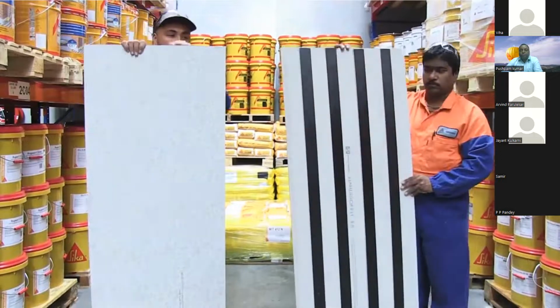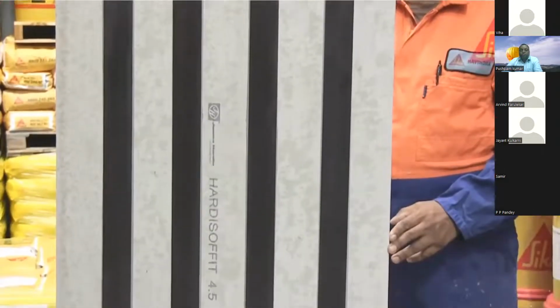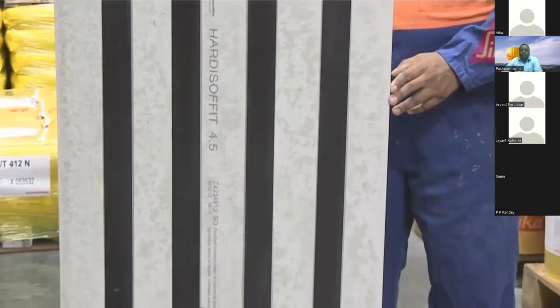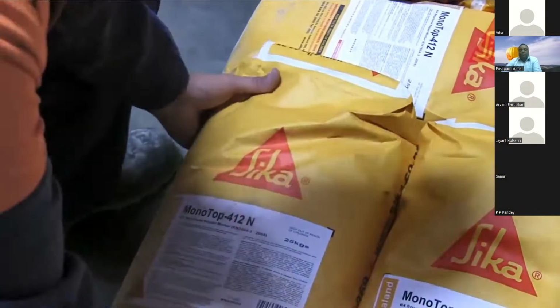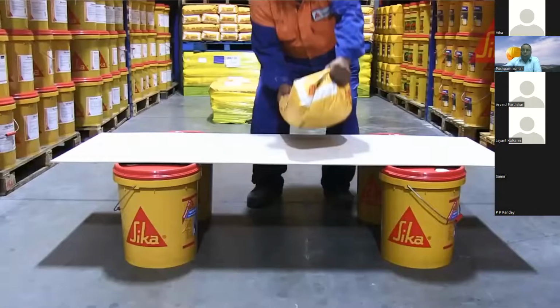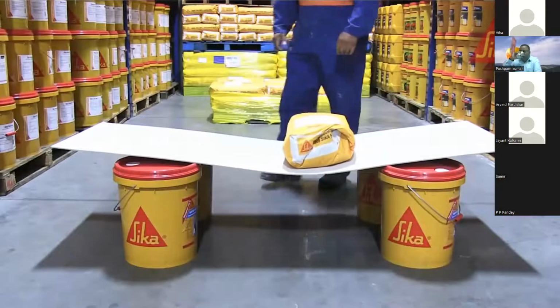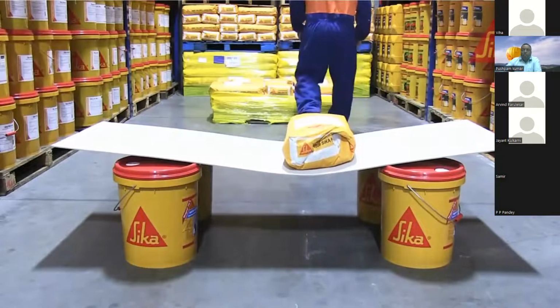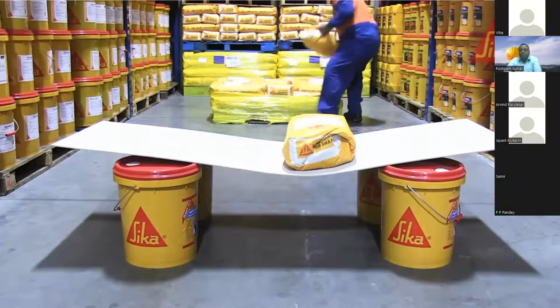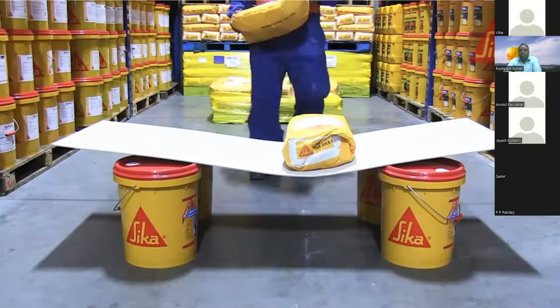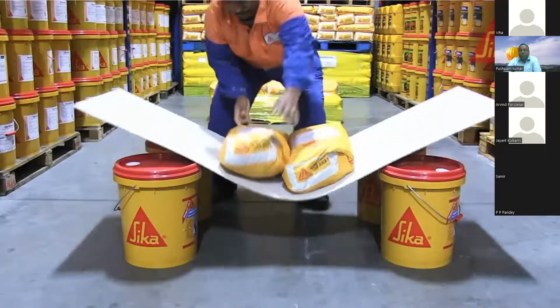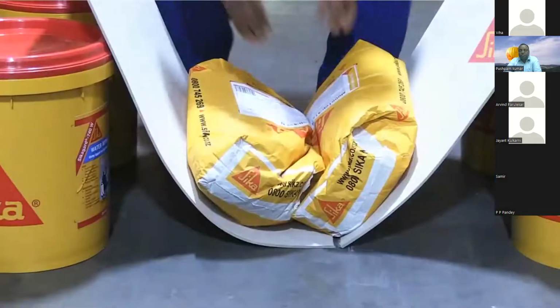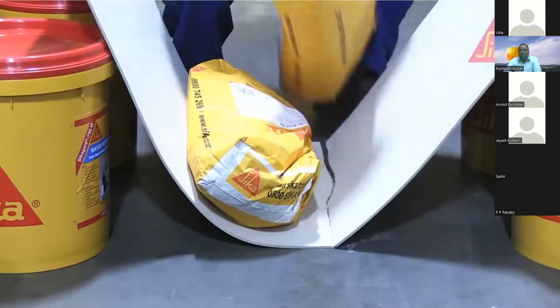The only difference being that one had been reinforced with Sika CarboDur strips. Then we put a 25 kilogram bag onto the unreinforced board. Then another 25 kilograms. And not surprisingly, it broke. No reflection on the fiberboard. It's not designed for this treatment anyway.